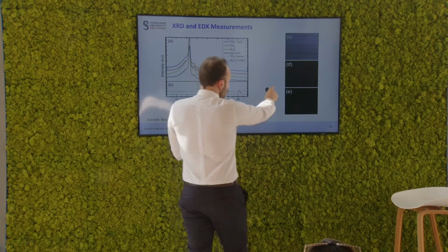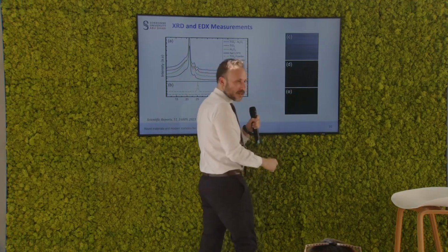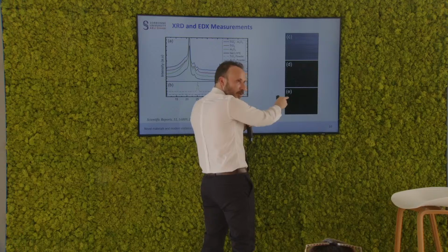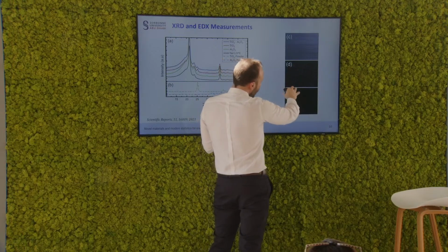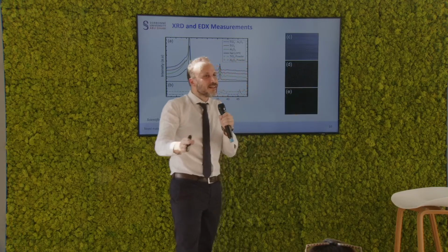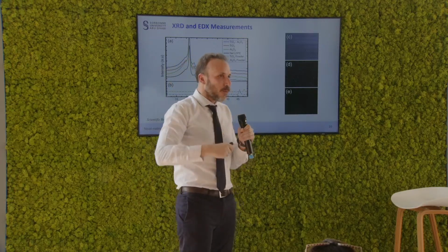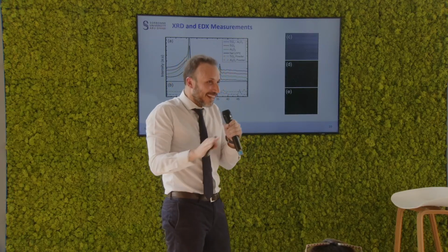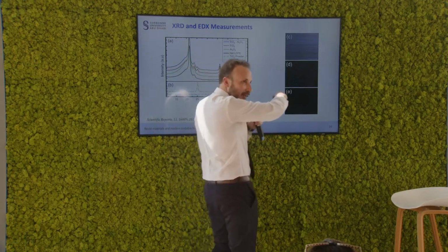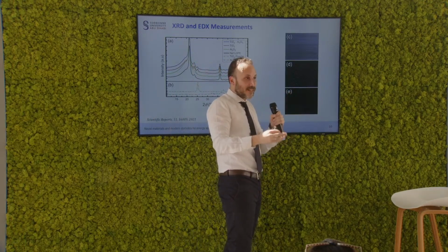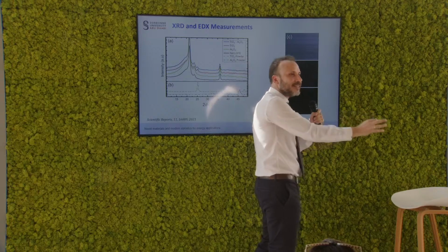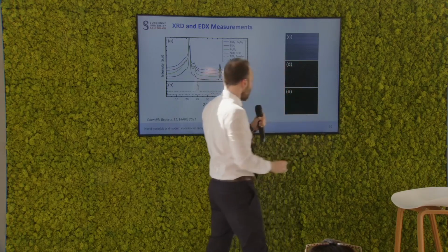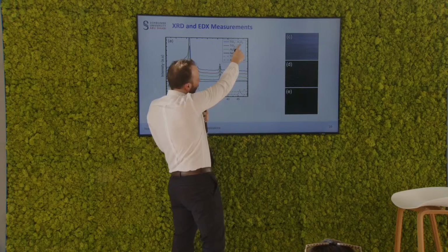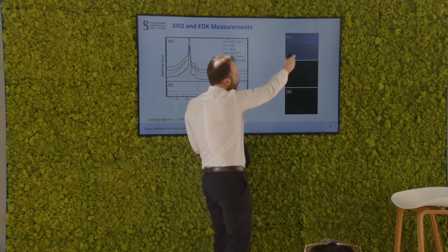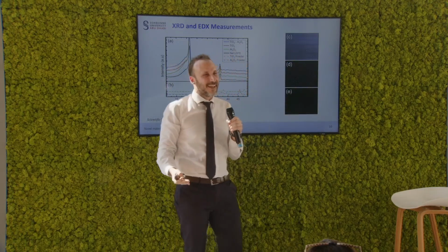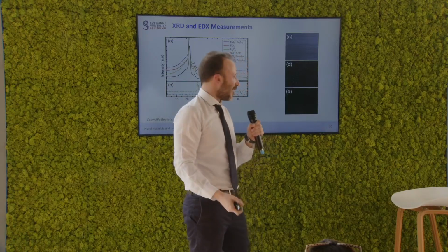So this is the position that you can find titanium cores, and this is the position where you can find aluminum cores. So they all seem to be of relatively the same size, but more importantly, they are all dispersed very evenly throughout the entire polymeric matrix without creating agglomerates and without being concentrated, isolated in certain places. This is actually coming from the titania alumina sample, which means all of these images are the same material by looking at different things every time.